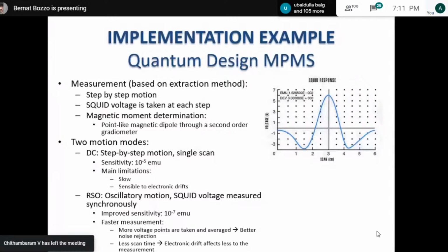Once we get this curve, this is the curve expected for a point-like dipole in a second order gradiometer. We can fit this curve, and from that fit we can determine the magnetic moment value of our sample. Basically, we can do the measurement in two ways. What we call the DC motion is this step-by-step motion that I just described. It has a simple construction, and it has a sensitivity.